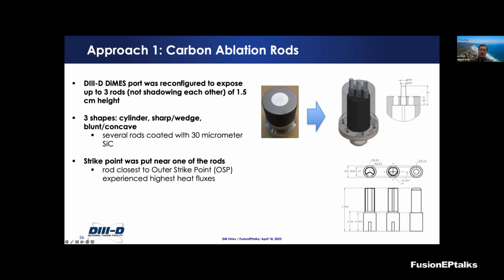The thinking behind that was that this cavity may actually be useful. It may trap neutral particles and have a little detachment region there, which might shield the carbon rod from the plasma heat fluxes, similar to how we achieve plasma detachment in divertor regions of tokamaks. By having this cushion of neutral gas, we could potentially lower the heat fluxes coming to the rods.